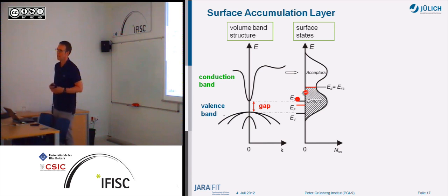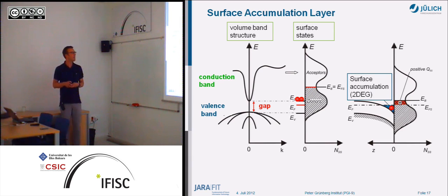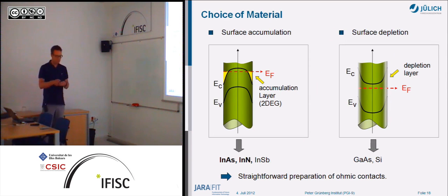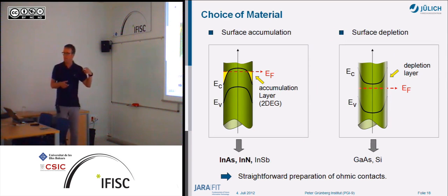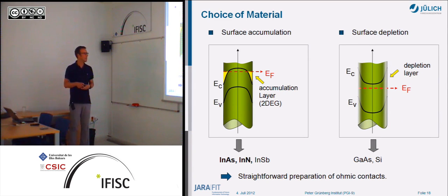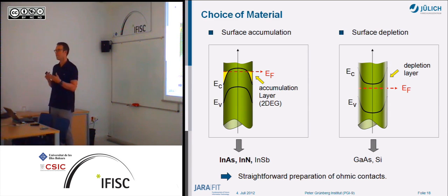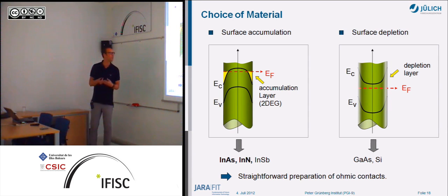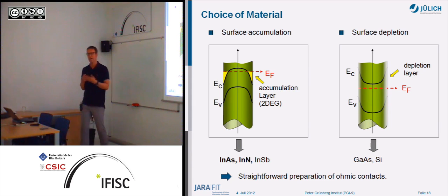And so if you, by a Gedanken experiment, attach both, then the electrons are getting transferred into the conduction band here because it's energetically favorable. And what happens is that you have a surface accumulation layer. So you accumulate electrons here, you're missing electrons here, you have a positive charge here, and electrons are transferred into the bulk semiconductor at the surface here, and you have a two-dimensional electron gas right at the surface. And this is, of course, a big advantage if you compare this kind of semiconductors with gallium arsenide. If you have indium arsenide, indium nitride, or indium antimonide, then you have the surface accumulation layer here, so you can be sure that you always have electrons in your nanowire. Now that's a big issue if you want to do transport experiments. You would like to have some electrons in your nanowire.